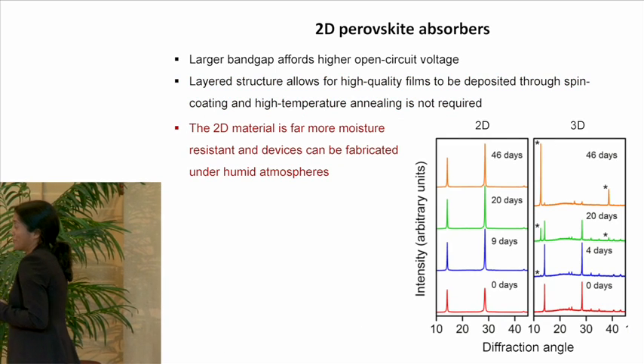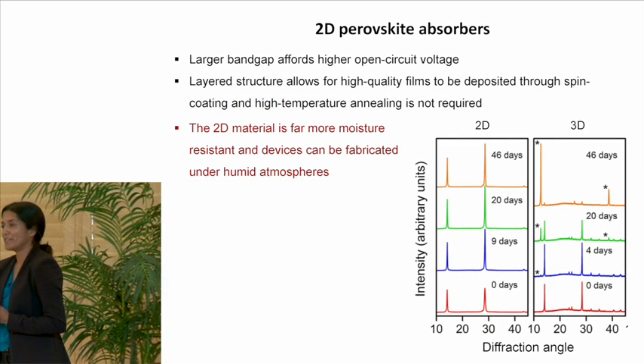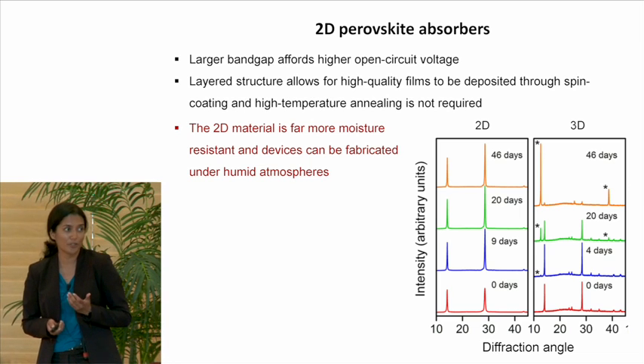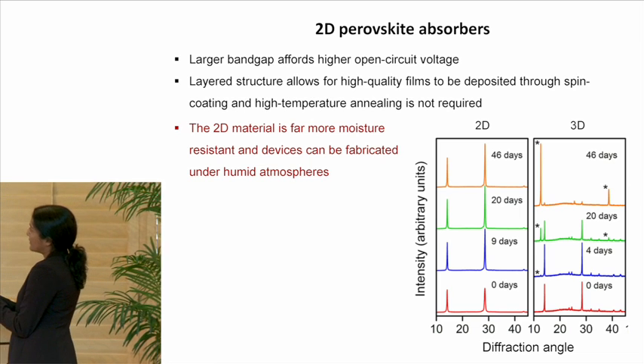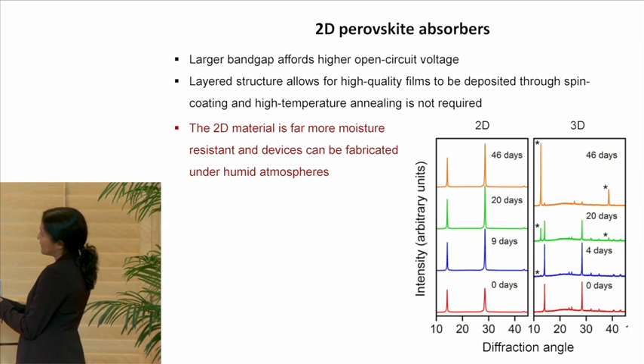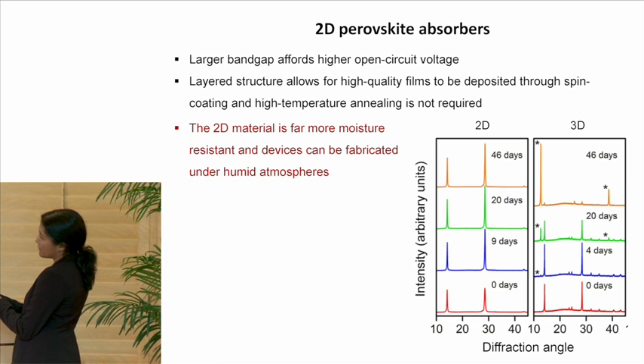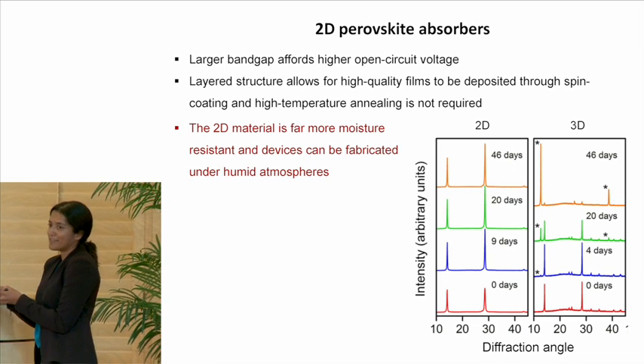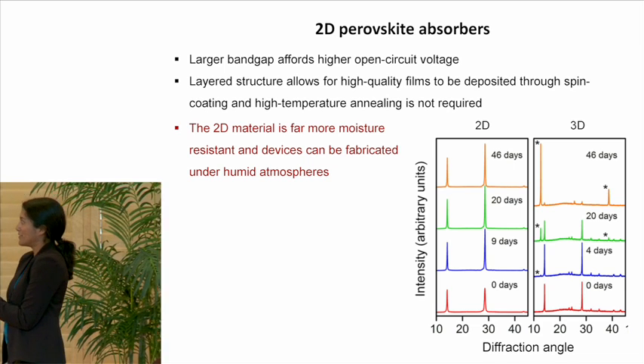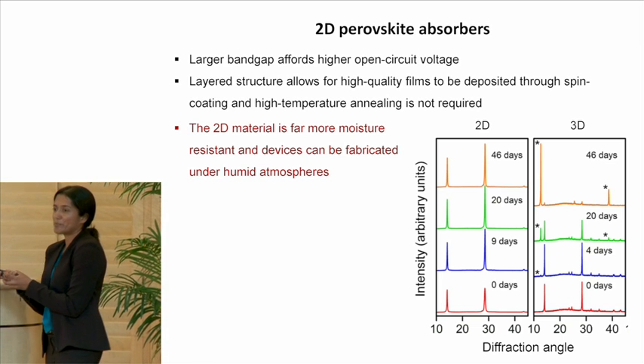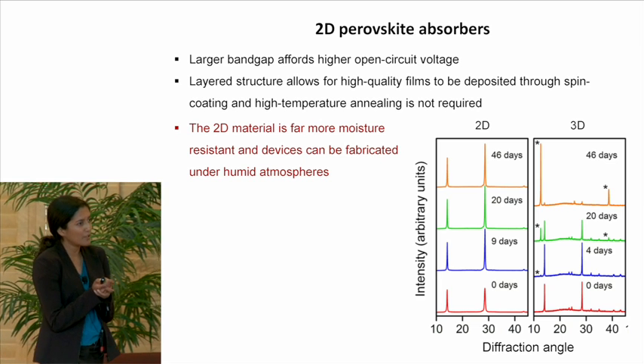And by far, I think the most important point here is that the 2D material is a lot more stable to moisture. So with the 3D material, here I show you powder XRD patterns, and over time, when this is exposed to about 50% humidity, we see the growth of new peaks, which completely dominate the spectrum after about 40 days. This is lead iodide, whereas in the 2D material, this material is pristine, untouched by lead iodide over 40 days.